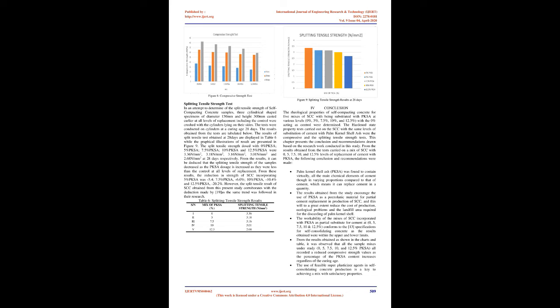The percentage variation in compressive strength of SCC dosed with 5%, 7.5%, 10%, and 12.5% PKSA, expressed in terms of their control sample, 0% PKSA, were -11.9%, -15.5%, -23.8%, and -33.8% respectively at 7 days, -6.8%, -8.3%, -13.2%, and -15.9% at 28 days, -7.1%, -11.2%, -18.3%, and -28.5% at 56 days respectively.